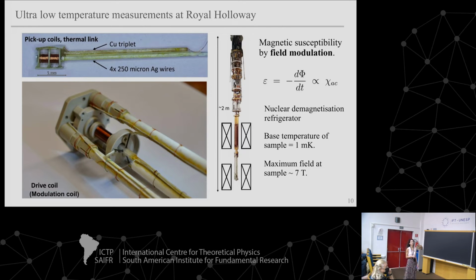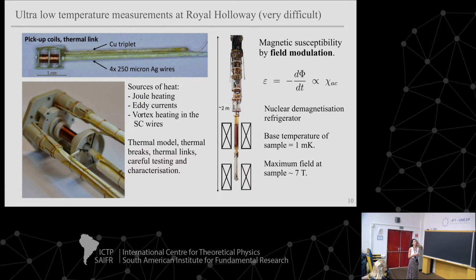Okay, so this is my only slide about the experiment, but it took us a very long time to get this right. We had a couple of attempts. Our first attempt, we couldn't cool below 30 millikelvin or so. But in the end, we got there. But just for the experimentalists, you can imagine with this type of measurement that there's a lot of heating, and we had to get all the heat out. So there's joule heating from all of the wires and all kinds of things. There are eddy currents because of the modulation field in the coils and in the sample and in everything else that's around there. And also, surprisingly, we had a lot of vortex heating from flux motion in the superconducting coil.